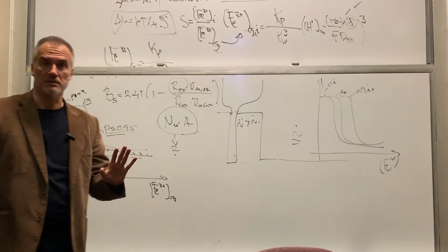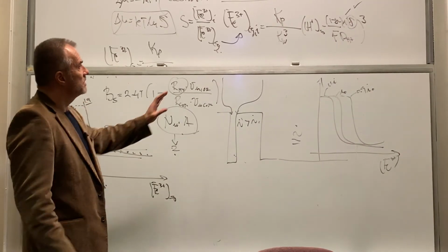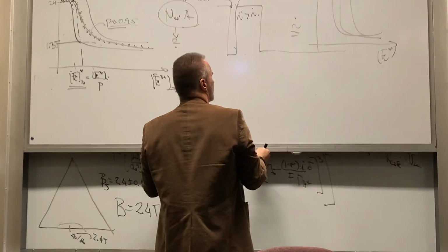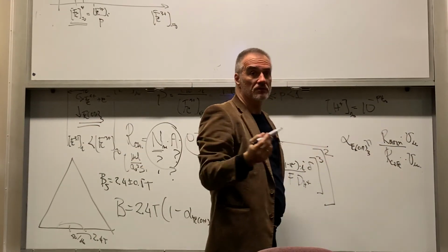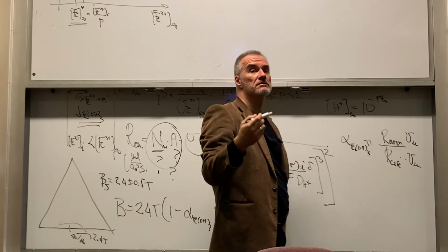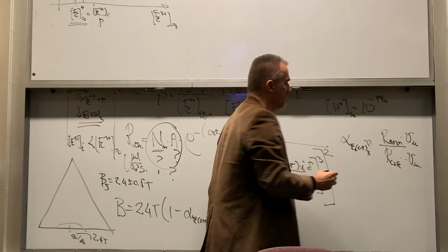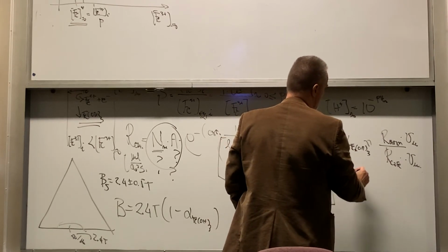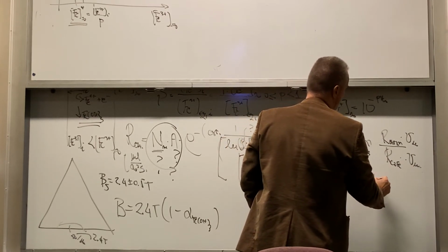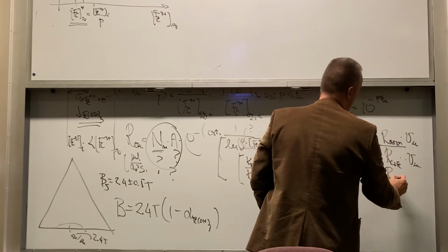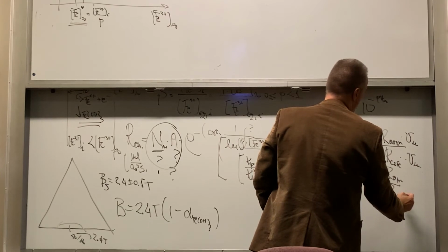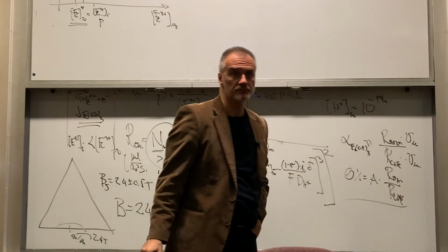Now, for the same reason, instead of measuring the volume fraction, we can measure the oxygen fraction, or just a fraction of the magnetic alloy. And so that really means if I say oxygen fraction, it will be some constant times the ratio between incorporation rate of the hydroxide versus the incorporation of the cobalt iron, for example, right?